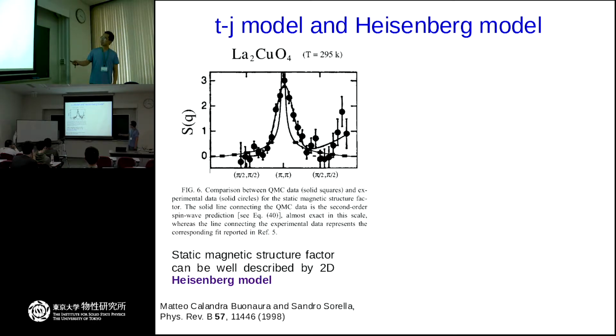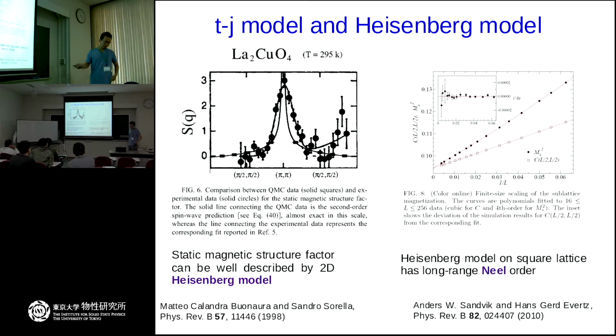Here I show you a result for the static magnetic structure factor from both simulation of the 2D Heisenberg model and from experiment for this correlated superconductor. The Fourier squares are from the numerical calculation of the two-dimensional Heisenberg model, and the Fourier circles are from experiment. We can see agreement between the simulation of the 2D Heisenberg model and the experiment, which is evidence that the Hubbard model can describe the physics of the correlated superconductor.